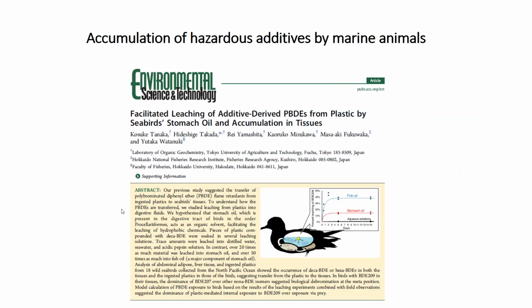And another thing that we've recently discovered, having contact with some colleagues in Japan, is that in a bird's digestive system, once they ingest plastic, they are likely to ingest fish as well, and other parts of their diet which contain oil. And if the plastic is present in the presence of oil as well as acid, that oil is likely to act as a facilitator to mobilize more contaminants from the matrix, because the oil is likely to act as a solvent and sort of denude the plastic itself.